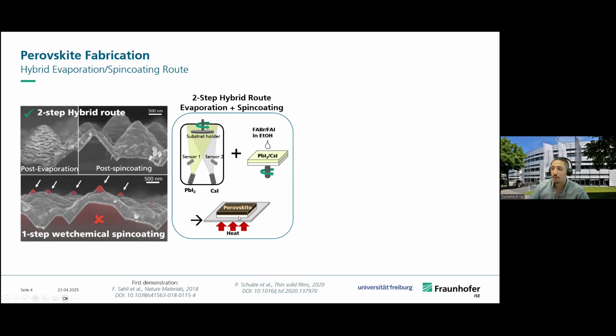So what is the hybrid method? It combines 2 different steps. In the first step, the inorganic precursors of the perovskite, so lead iodide, for example, and cesium iodide, are evaporated in order to form a conformal inorganic scaffold or template on top of textured silicon. So typically we use lead iodide and cesium iodide, but some other researchers also use cesium bromide. And in terms of the rates, usually we have 1 angstrom per second here, and here around 0.1 angstroms per second, so around a 10% ratio.